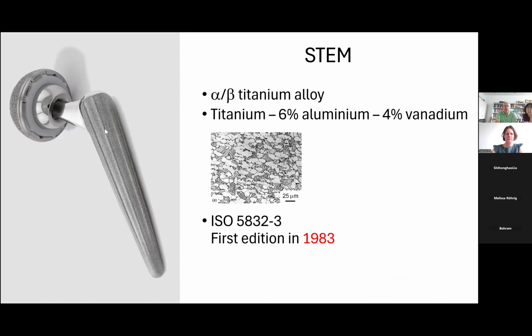But if you look at a hip joint, you have the stem. The stem is usually made in an alpha-beta titanium alloy. It means you have titanium, 6% aluminum, and 4% vanadium. You have the alpha-beta structure. And you can see here the first edition of this ISO was made already in 1983.